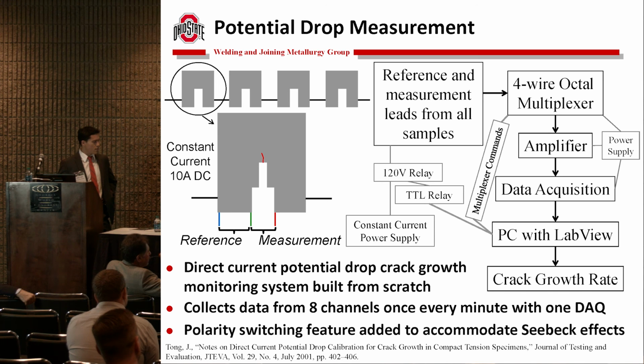Currently I'm working on updating this to have a polarity switching feature, so Seebeck effects can be accommodated for, because if cracking is going to happen so quickly, now I need to worry about the initial heat up, and I need to be able to subtract out those changes in voltage with temperature.